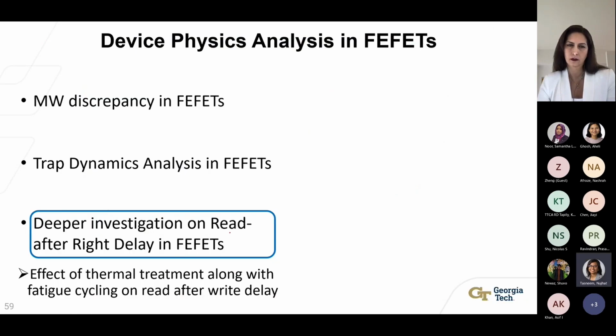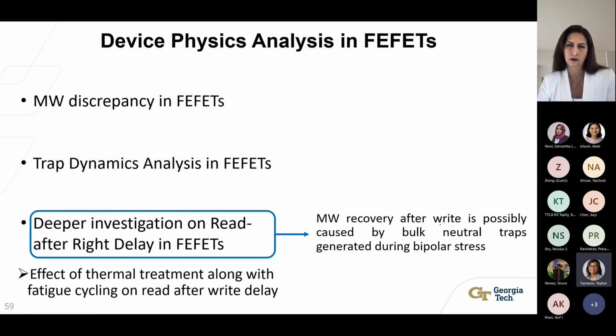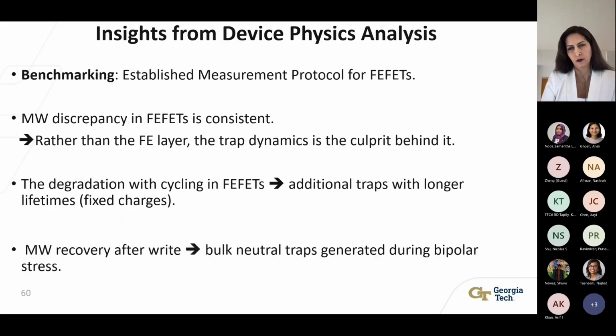So our deeper investigation on read after write delay showed us that this delay in p-type FeFET is possibly caused by bulk neutral traps generated during bipolar stress and linked to breakdown. So these are some of the insights that we got from our device physics analysis of FFETs. So we were able to establish a measurement protocol, the 3-step measurement protocol, to determine the efficiency in practical FFETs and benchmarking them. We also learned that the memory window discrepancy in FeFET is consistent, and rather than the ferroelectric layer, the trap dynamics is the culprit behind it. We saw that the degradation with cycling in FFETs is caused by additional traps with longer lifetime. Also, the read after write delay in PFETs is possibly caused by bulk neutral traps generated during bipolar stress.